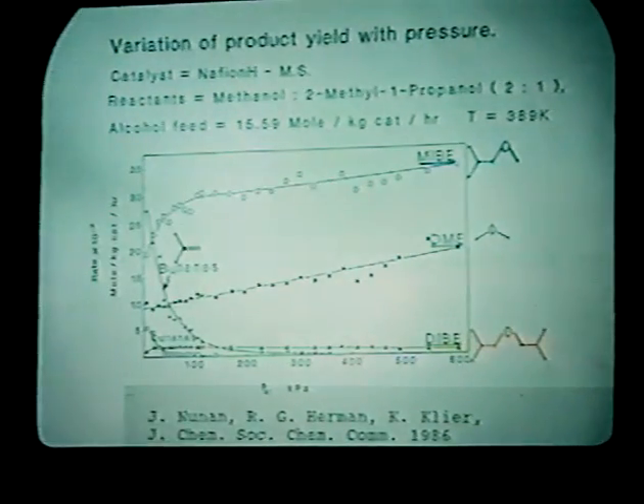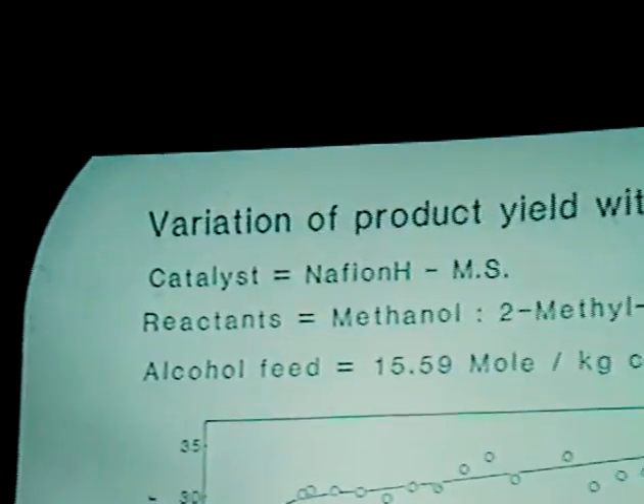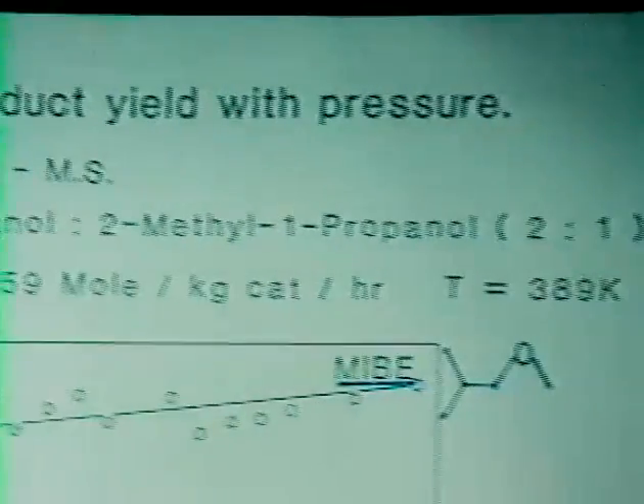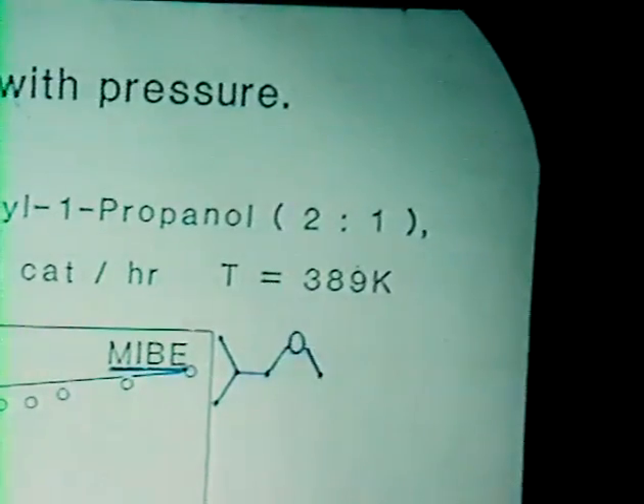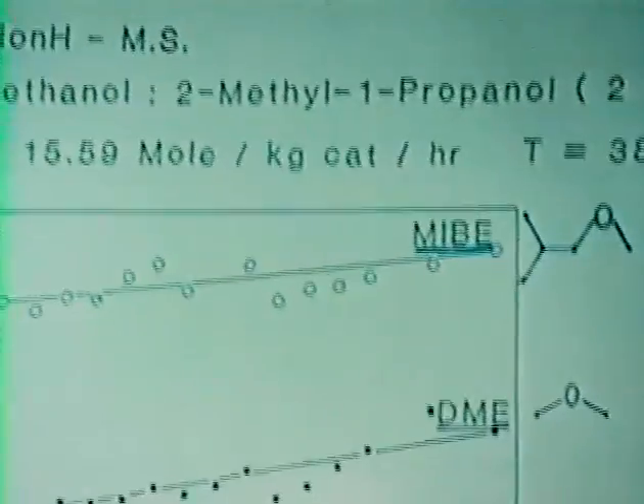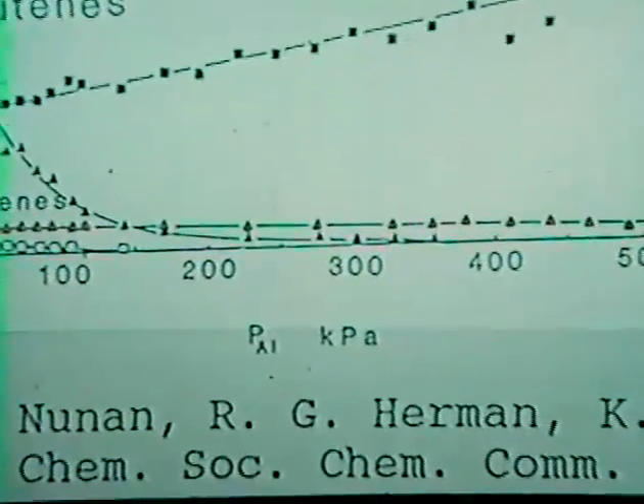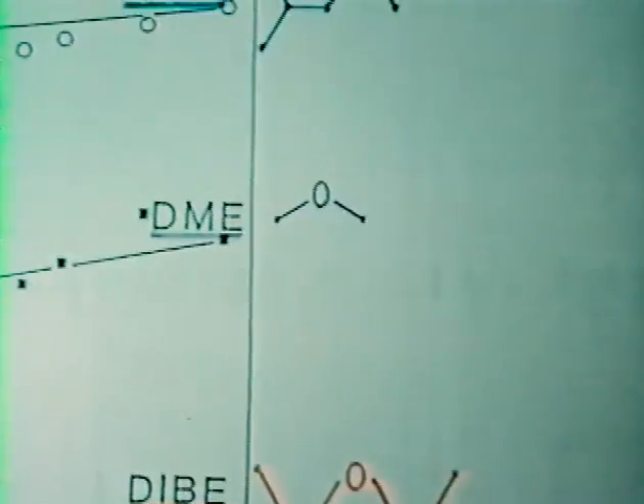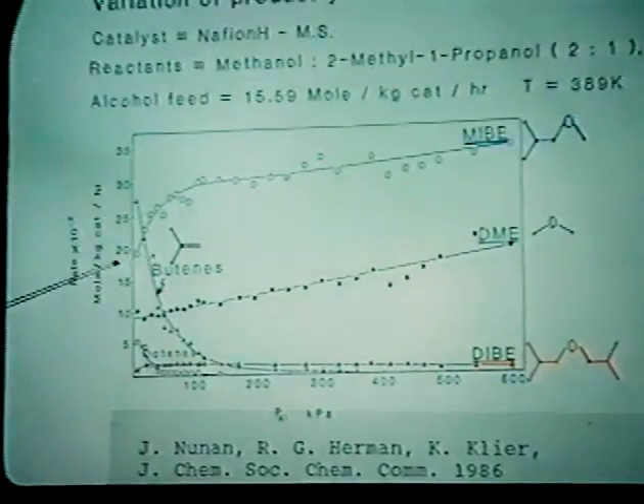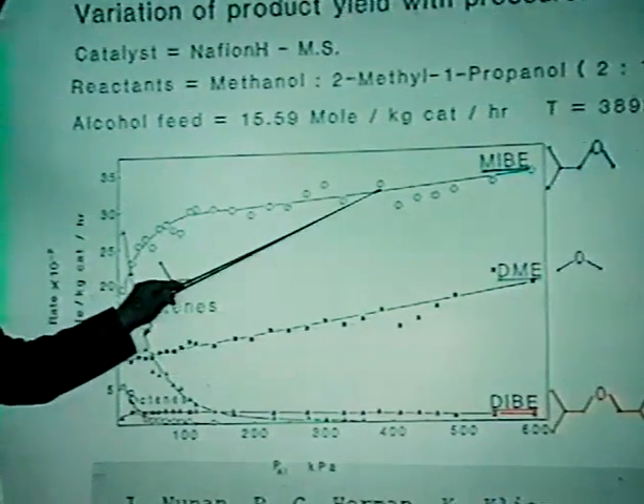So we entered an area new to us and used an acid. And what's better than an acid is a superacid. And so we used superacidic resins. They are in kind of a semi-market or gray market, I call it, Nafion H here, which does the following. You take the methanol to isobutanol ratio of 2:1, just as it's coming from the previous synthesis, and you follow the products as a function of pressure. At low pressures, indeed as expected, the isobutanol will dehydrate primarily to isobutene. But as you increase the pressure, that reaction will be rapidly suppressed in favor of reactions that give rise to ethers. But the ether is not MTBE.